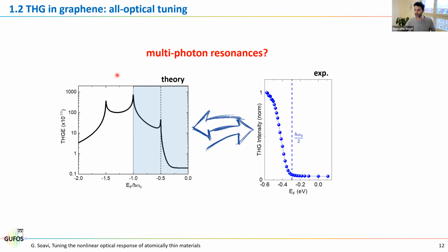And indeed, if we look again, the theory predicts that at this point where ħω0 equals 2 times EF, so this peak here is the one photon transition, here we would expect to have a peak, so a maximum. Instead, when we look at experimental data, we only have the onset of the build-up. So there is quite a large discrepancy between the theory and the experiments.